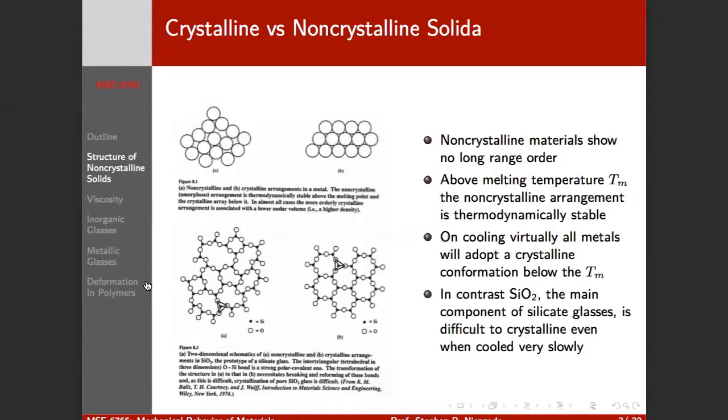And the same thing happens in a metallic glass. It's not really like a liquid structure, because even in a liquid, the very local neighborhood is very much the same as the crystal. So basically, if you have a metallic glass, if you take a metal that normally makes BCC and you cool it down quickly enough, we'll talk about what quickly enough means in a minute, each atom is still in a very close approximation to the BCC structure, because if you deviated too far from that, the atoms wouldn't be happy.